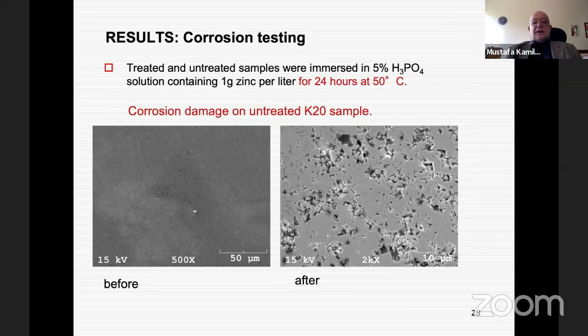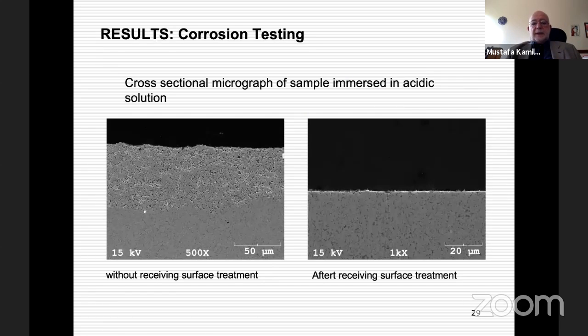So for testing if we have achieved our aim, we have conducted corrosion tests. So this is the surface of the sample before the treatment and before the corrosion test. When you subject this material to a corrosion test, for 24 hours at 50 degrees, you see that the cobalt phase is being leached out, leaving behind tungsten carbide particles that fall into the solution and deteriorate the mechanical properties. And when we look at the cross-section of the same sample, we see a dramatic effect of corrosion that expanded up to 50 microns of depth. You see all these dark spots, the areas where the cobalt is being leached out.